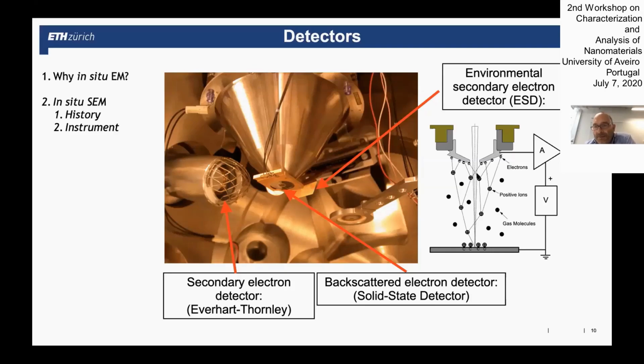And here on the right side, there's a schematic drawing. Here, this gaseous secondary electron detector is symmetrical around the primary beam. It doesn't matter here, it's just on the side, but it can also be directly under the central part of the beam. But the function is very simple. You put it on a positive potential. So here it's just really a metallic plate that you put on a positive potential. When the electron beam hits the sample, it induces the formation of secondary electrons. And these negative secondary electrons get accelerated towards this positive metal plate, this detector.